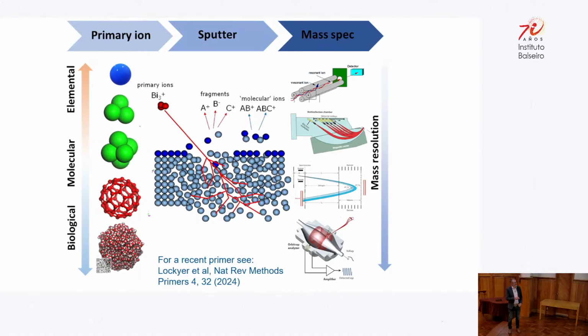This is the fundamental process that goes on. We fire ions in at the surface. We set in motion molecules below, the atoms and molecules below the substrate. But some of that energy comes back to the surface, and then we desorb atoms and molecules. And these days we can desorb quite large intact proteins into the gas phase. These are then detected in whichever mass spectrometry you prefer, from quadrupole, magnetic sector, time of flight, or Fourier transform instruments.